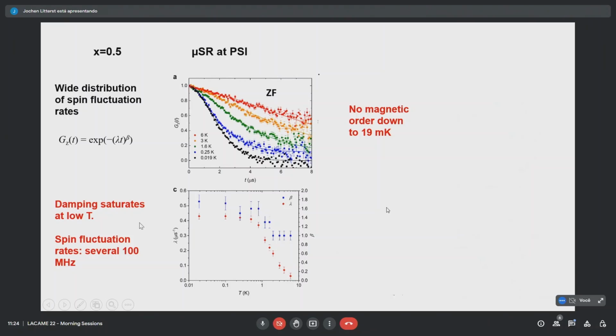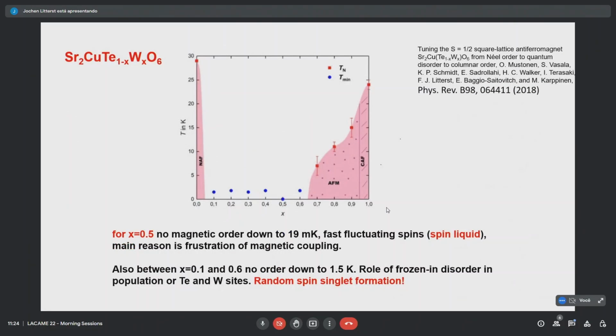Typical signature of the spin liquid. In this case, it's indeed a quantum effect since we see it only at very low temperature. The Curie-Weiss temperature actually is around 50 to 80 degrees, much, much higher. So we could derive a phase diagram of that. We found no order, not only at 0.5, but over a wider range, just in the middle of this gap between the tellurium and the tungsten compound.